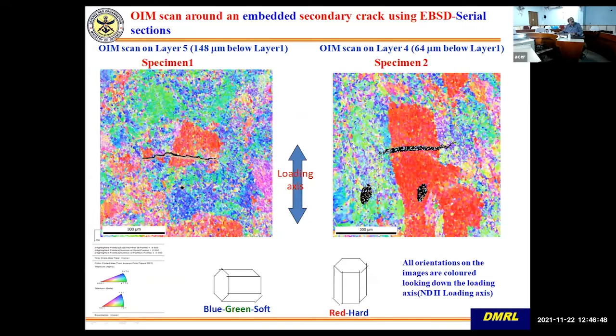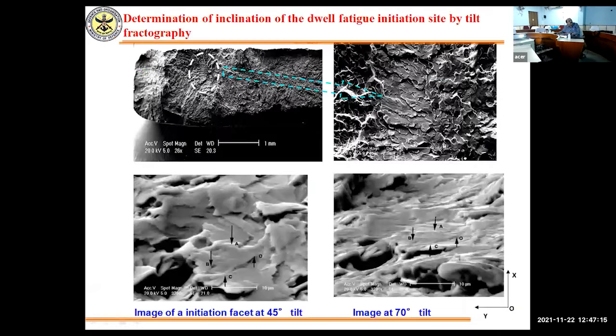So red means hard. So that is C axis is oriented in the loading axis. So there is no resolved shear stress on the basal plane or on the prismatic plane. Only the C plus A hard orientation can deform. So as I told, these deform soft and unload onto the hard region, and these crack. So this is the phenomena, and you can see this is fully embedded. A crack is inside the material. It is not on the surface. And this is the main crack.